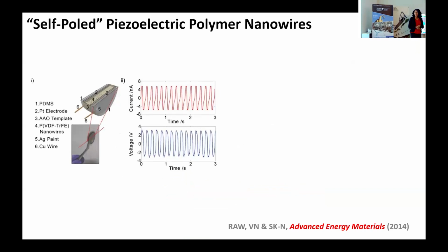The other thing we observed is that you could make devices out of this straight away. So I was keen to see whether this works. And I was like, right, brute force method. Let's put some electrodes across this device. So here's our template with all the nanowires. We put some electrodes. So this is kind of what it looks like. It's a very thin membrane packed with these aligned nanowires. And the first experiment was just tap on it, like just apply a little pressure and see whether you can see an electrical response. And you do actually get a current and voltage output.